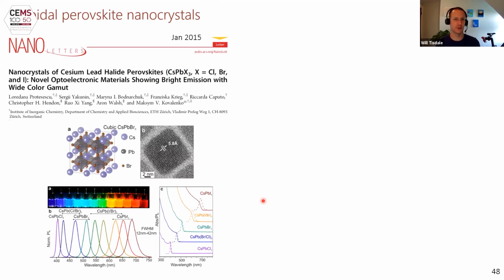Perovskites make terrific solar cells. If they're such defect-free, wonderful semiconductors, then they should also make great quantum dots. And indeed they do. The seminal work in this area was out of Maxim Kovalenko's group at ETH. They synthesized cesium lead halide nanocrystals about 5 years ago at this point. This is a now highly cited paper. Many people in the quantum dot community are working with these materials these days, our group included.